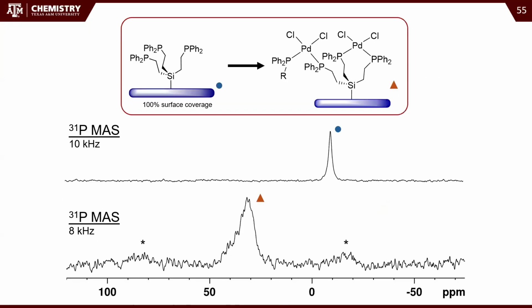Then we can make our palladium complex. If we have 100% surface coverage and we add our palladium, we actually consume all of the phosphine, so there's no more leftover ligand signal. And the palladium should only coordinate 2 phosphines. What that's telling us is that we're actually sharing between ligands, which kind of makes sense. If you're supposed to have 100% surface coverage, it would make sense that you have phosphines that are relatively close together. So we consume all of those phosphines, and I think that's because we're sharing between ligands.